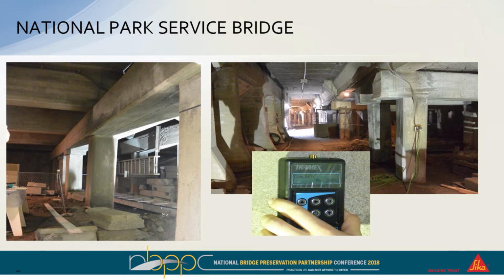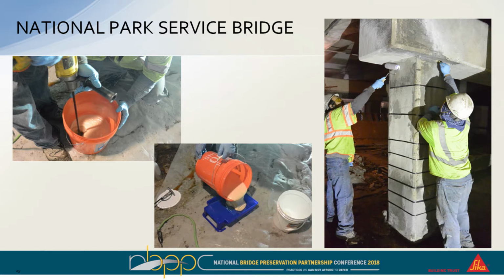Here you have a moisture meter to measure the moisture content in the concrete. Typically, if you're over about 4% moisture, that's when you don't want to use epoxies. You want to either dehumidify it or wait for it to dry out. In this case, they were able to get onto it because they had no moisture issues with the moisture-cured resin. Here you see the application of the primer onto the concrete.